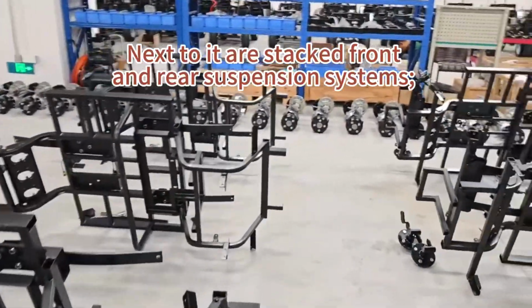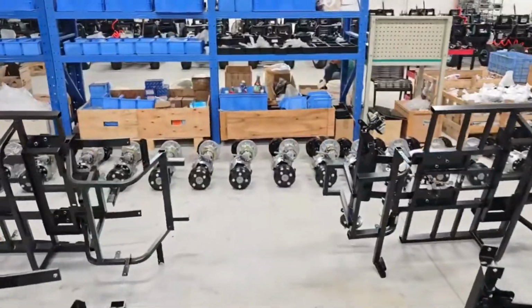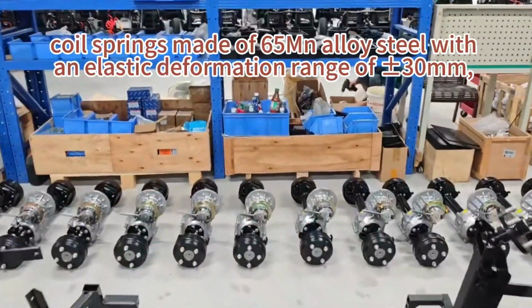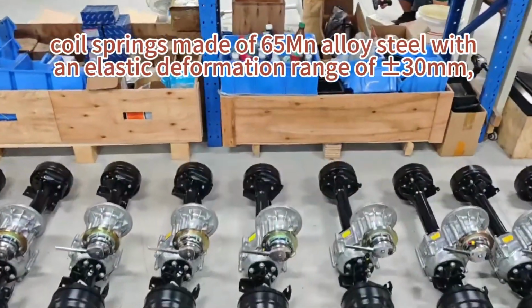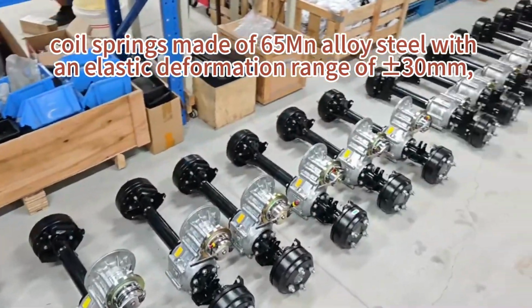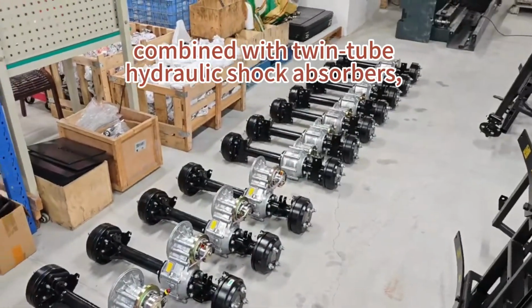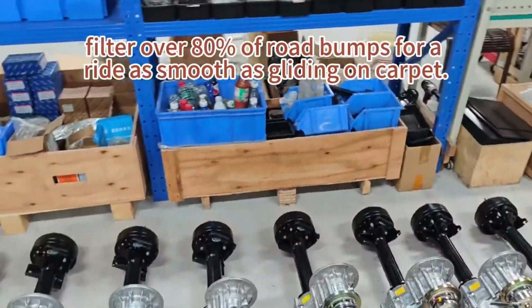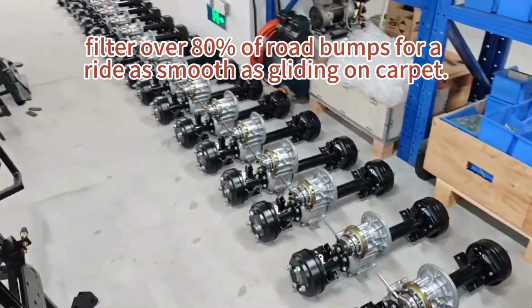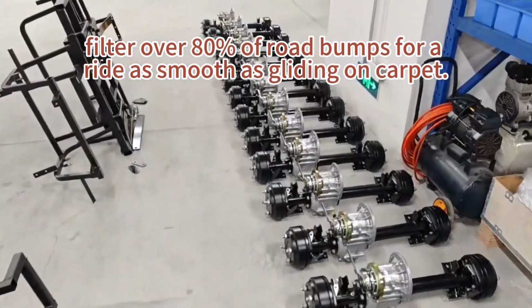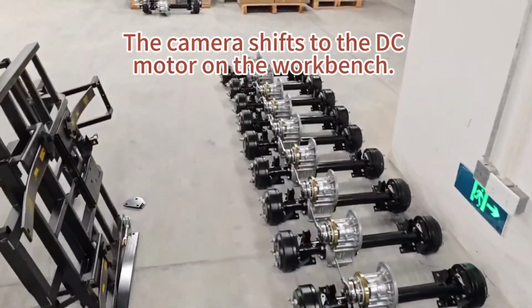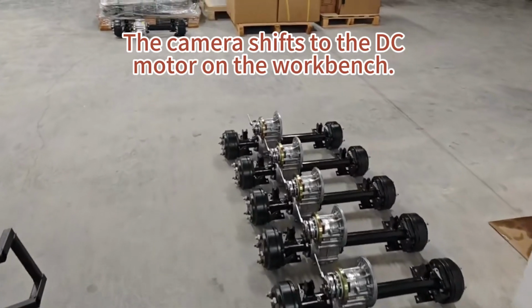Next to it are stacked front and rear suspension systems, coil springs made of 65 Mn alloy steel with an elastic deformation range of plus or minus 30 mm, combined with twin-tube hydraulic shock absorbers, filter over 80% of road bumps for a ride as smooth as gliding on carpet. The camera shifts to the DC motor on the workbench.